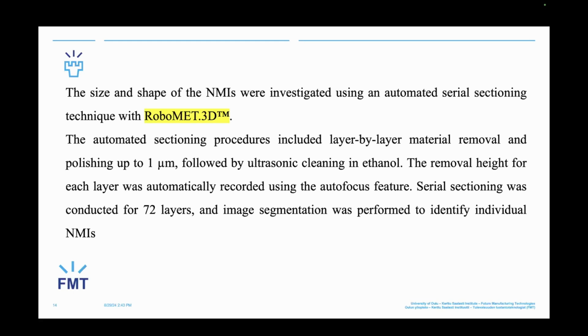It makes another 10 micrometers of mechanical polishing and takes another image. After 72 images, it reconstructs the images and gives you the 3D dimensions of the non-metallic inclusions. It's very interesting, and this new microscope is at the Forschungszentrum. Later I will present the RoboMet results to see how this technique can be used to detect any defect in the material.